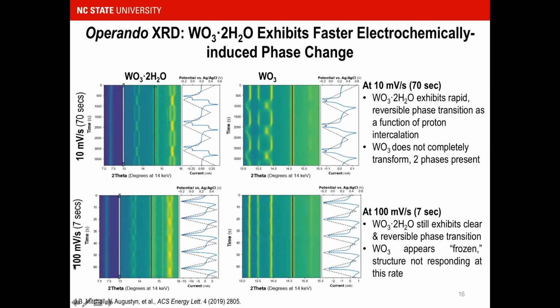If we push the materials faster to 100 millivolts per second, now we're going to a 7-second charge discharge time, that hydrated material is still able to keep up with that phase transformation, whereas the anhydrous one essentially appears frozen. And this is directly tied in to the capacity that we obtain from both of these materials at the very fast rates that we're interested in.